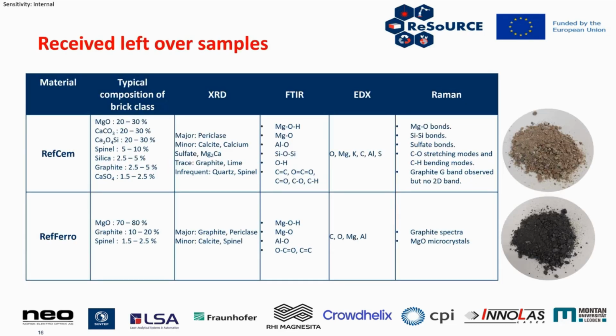So we first looked at the chemical composition of these spent materials. And broadly, we can see that they're comparable to what we might expect to be used within the bricks. So for instance, we see a lot of magnesium oxide in there and calcium species like calcium carbonate. We see these across a range of different characterization techniques: the XRD, FTIR, EDX, and the Raman.